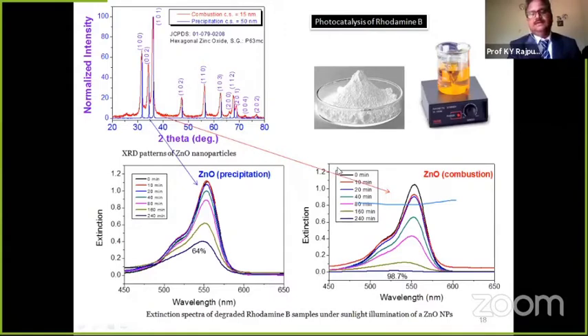So it is seen that the degradation of rhodamine B, which is an organic chemical compound whose color is orange, occurs with time. When you disperse this zinc oxide powder, whether polycrystalline or nanocrystalline, in the solution of rhodamine B, illuminate the solution and continuously stir it, we see that with respect to time the color of the rhodamine B gets faint, and the rhodamine B gets degraded completely, maybe after 40 minutes or so.